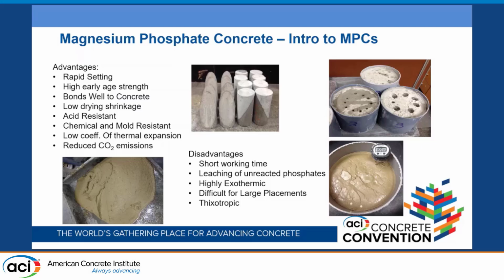And then it's highly exothermic. I mean, that's in a third of a 6x12, and we're at 170 degrees on the edge of it. And so it's also difficult for large placements. And then it's thixotropic, which means that when you agitate it, it becomes more flowable. And then when you stop agitation, it starts to solidify, but not necessarily set. And so, yeah, that one is fun. We were supposed to be doing time of set on them, but it didn't go well for us.